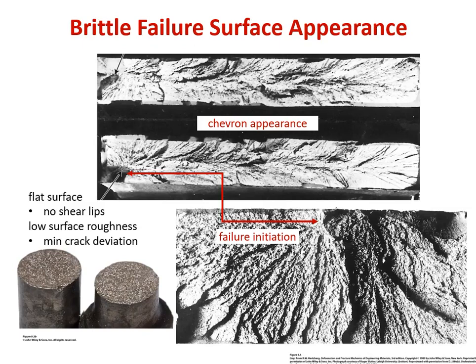In practice, we'll get quite often a chevron appearance, where if you trace the pattern of the chevrons back, quite often you can find the initiation point. That's not always the case, but it's certainly a tool that can be used to try to identify what may have been the initiation cause. Quite often it's a surface defect, a corrosion pit, or even a fatigue initiator, which we'll talk more about later. But generally, to recap, ductile fracture, lots of topography, usually shear lips out on the outer surface, brittle fracture, much, much smoother, and much more straight across, perpendicular to whatever the tensile loading axis was.